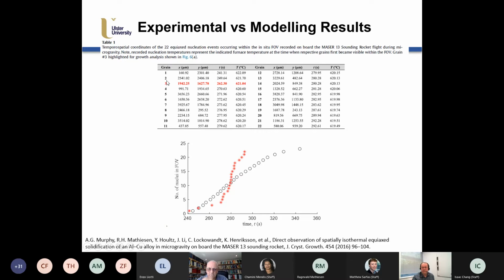You have all of the grains. There were 22 crystals observed in this field of view, and you have the locations, and you have the timestamp, and you have the furnace temperature, not the sample temperature, but the furnace temperature. Just to give you an idea, the liquidus temperature for this alloy, aluminium 28% copper, is around 603 degrees Celsius. So these aren't representative of the sample, but we were able to look at this on average and get here.